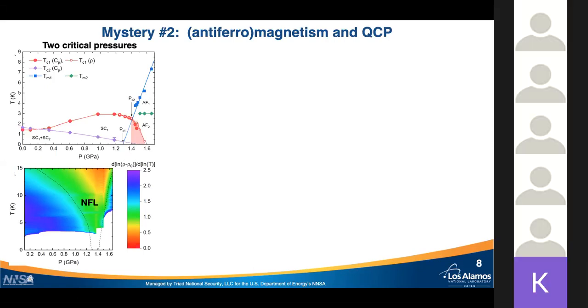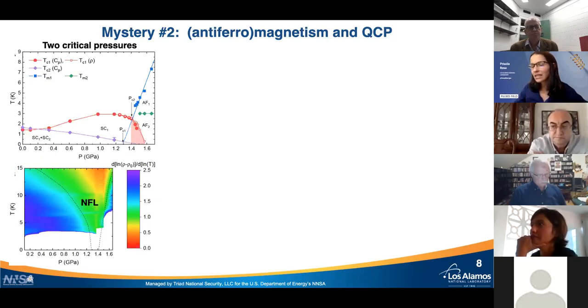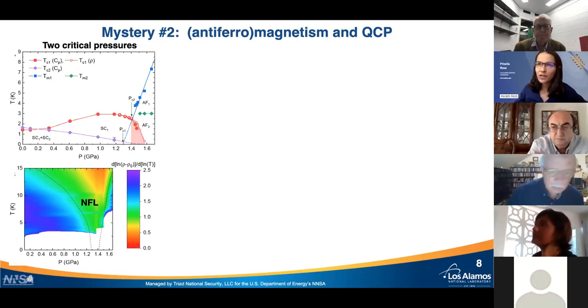Right. So actually a lot of that has been done even at ambient pressure, but no quantum oscillations have been observed so far, which is a little surprising to me. At fields below 20 Tesla, actually the magnetoresistance is not very large. So that could be related to a couple of things. Well, first, if the sample is not perfect, you may have scattering from disorder, messing up things for you. But also, we know that there are strong magnetic fluctuations in this material. And if you have strong magnetic fluctuations, you may not get to a regime where omega c tau is larger than 1. So unfortunately, we don't have fermiology from quantum oscillations yet. But that's an interesting point.